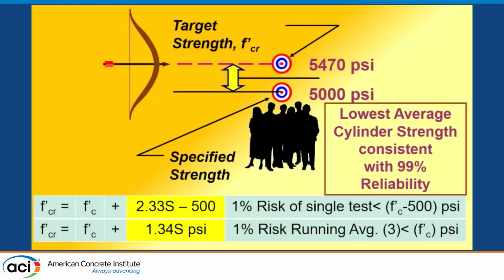And all that statistics boils down to a couple simple equations. Our target strength is going to be specified strength plus this, 2.33S, and for our 5,000 PSI example, we got a bargain in the industry today. Tell you what, we're going to mark that strength down 500 PSI. Mark them down and move them out. So we're going to give you a free 500 PSI. And then we're going to say, I want a 1% risk of getting lower than that.